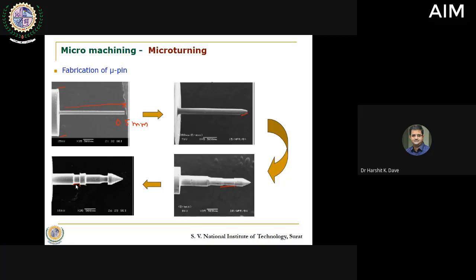So theoretically, even though it is possible to generate micro features with a conventional machine, practically the problem that we encounter is the deflection of this micro shaft, which would eventually lead to its breakage. So often this does not work. Out of maybe around 300 plus experiments that we tried, luckily we could get some 20-25 odd conditions, at least 10%, where we could generate the shaft. Otherwise it was breaking, even with the micro machining setup. So in a way, this deflection is a very big issue.